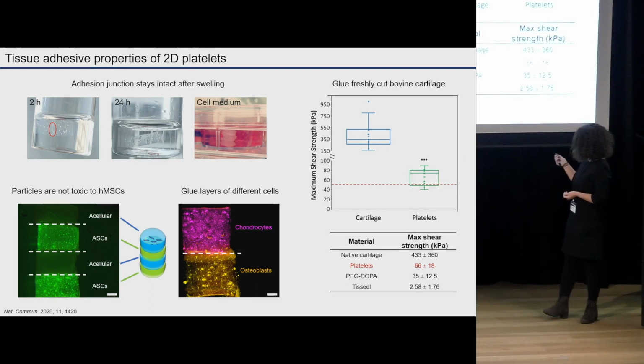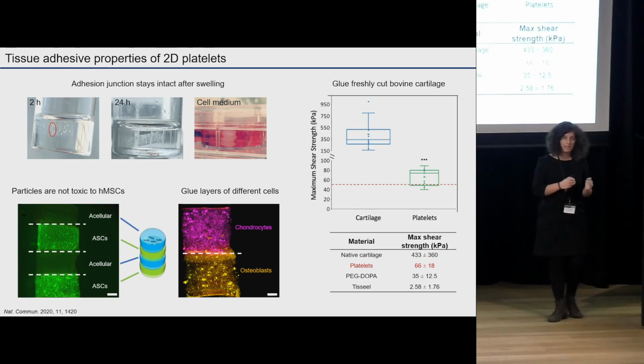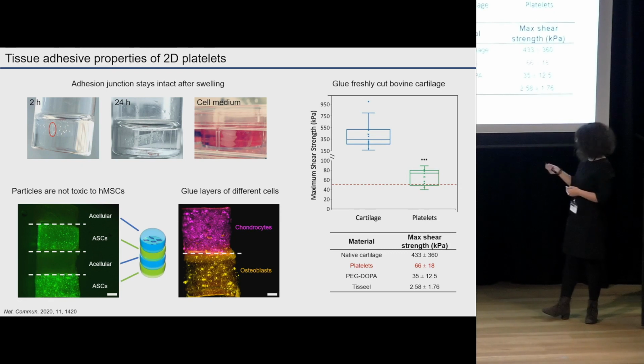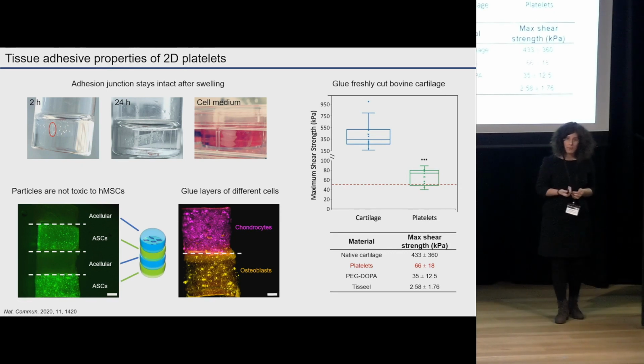And as you can see here, with the value of the shear strength, so the adhesive strength of these nanoparticles, they're actually comparable, if not better, with some of the materials that have been approved as adhesives for internal use, such as the PEG-DOPA and the Tisseel adhesives, so fibrin-based adhesives.